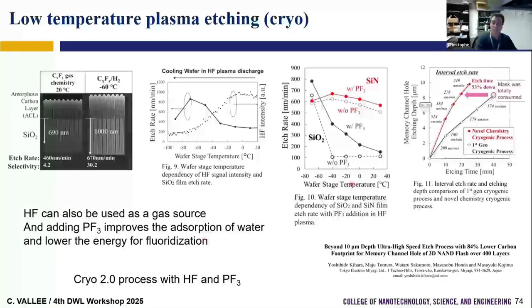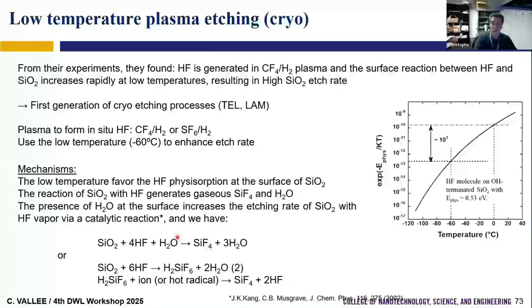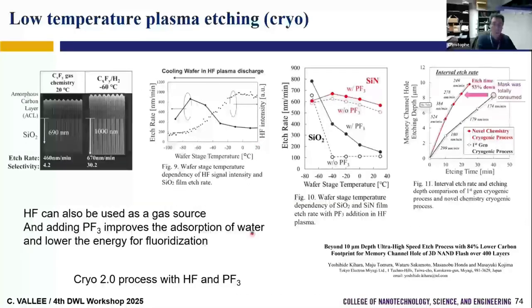So this is what we call the first cryo etching tool, for example, the LAM 1.0 cryo etching tool. And for the 2.0 process, people proposed to directly introduce HF and to do an HF plasma. Instead of using CF4/H2 or SF6/H2, we can directly inject HF in the plasma discharge. And they also found that if you add some gas like PF3, it will also have a catalytic effect, and we promote the etching.